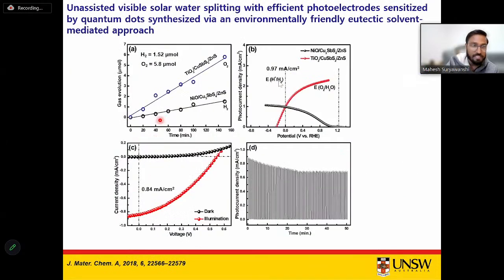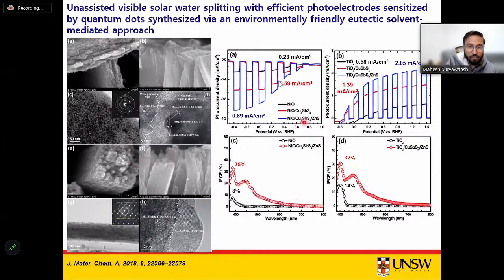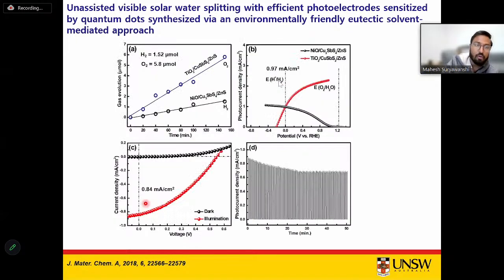So what we have done is we have prepared some quantum dots of this copper antimony sulfide, and then we have sensitized these copper antimony sulfide quantum dots on nickel oxide nanosheets, and again on TiO2 nanorod arrays, as a p-type photocathode and as an n-type photoanode. And then we have fabricated this two photoelectrode system to produce the hydrogen and oxygen without applying any additional bias.